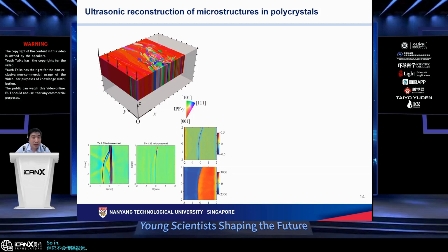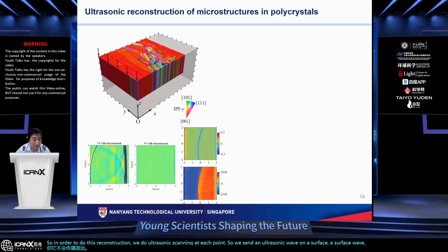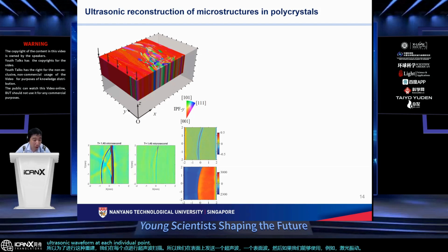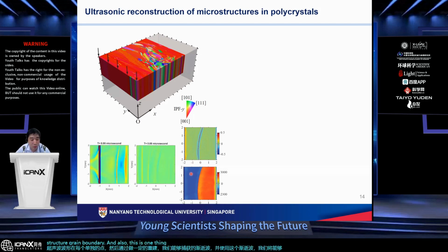So in order to do this reconstruction, we do ultrasonic scanning at each point. We send an ultrasonic surface wave, and then we use, for example, a laser vibrometer to pick up the local ultrasonic waveform at each individual point. By doing certain reconstructions, we are able to capture the evanescent wave, and using this evanescent wave, we are able to reconstruct the grain boundary. Also, we are able to reconstruct the velocity of Rayleigh waves, which tells certain information about the texture.